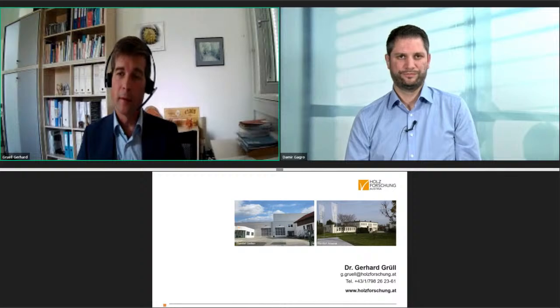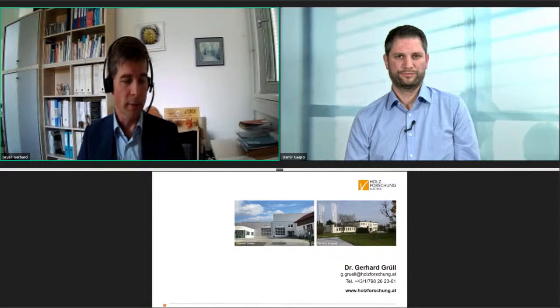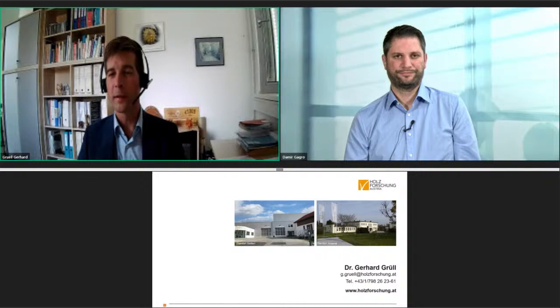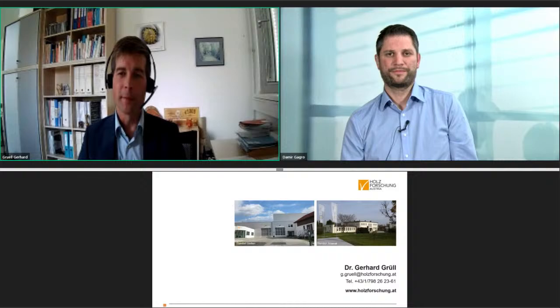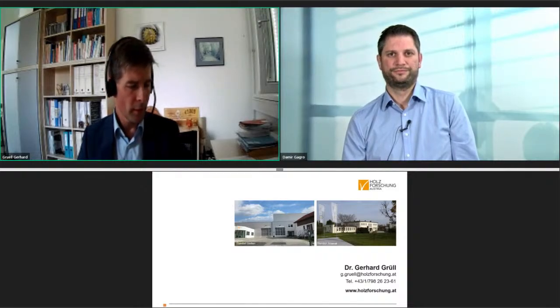So it's a very beautiful, nice structure with hardly any grain deviations and so on. So from the wood quality, the acetylated wood on the European market is very nice. As a coating substrate, we have had one study where it was also good, also in comparison to other substrates. I myself have no real experience if this is due to the modification by acetylation or if it's more like the influence of wood quality of the material we use in this study.